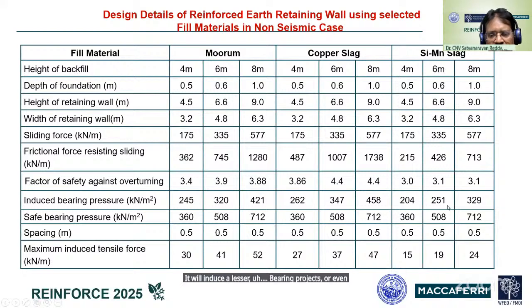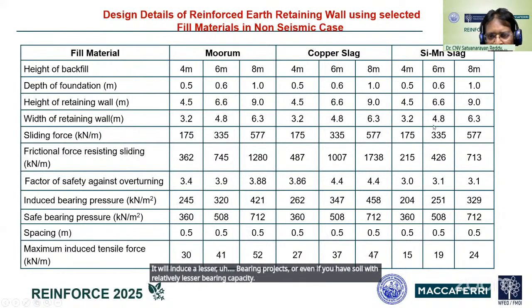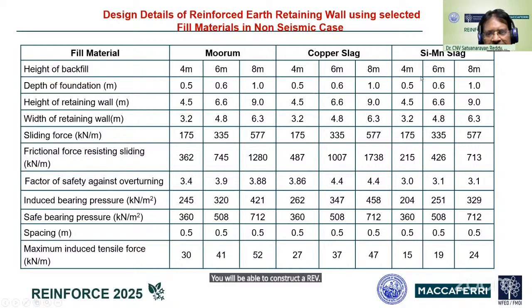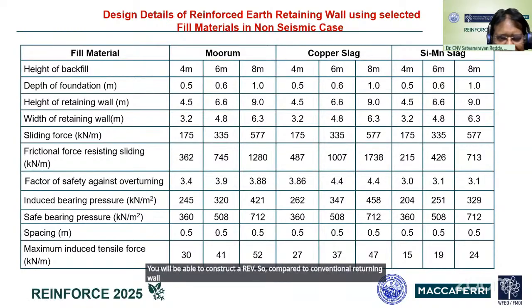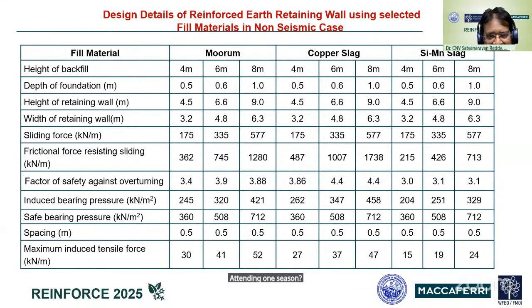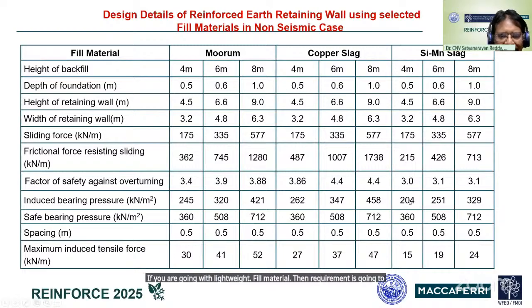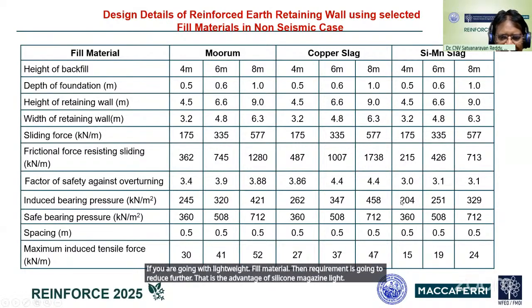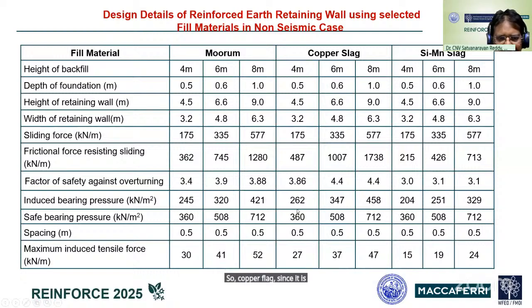So using silico-manganese slag for retaining backfill of a given height will induce lesser bearing pressures. So even if you have soil with relatively lesser bearing capacity, you will be able to construct an RE wall. Compared to conventional retaining walls, the bearing capacity requirement for reinforced earth retaining walls is less. Even in reinforced earth retaining walls, if you go with lightweight fill material, the requirement reduces further. That is the advantage of silico-manganese slag. Copper slag, since it is a heavy material, has resulted in an increase in bearing pressures. So unless you have reasonably good foundation soil, don't select copper slag even though it is available locally.